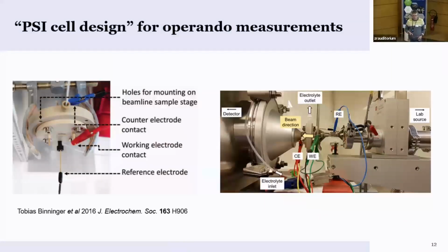Of course, important in this is to have electrochemical cells that allow these measurements. And basically, we use two different configurations of cells. One, which I just call the PSI design, was introduced at the PSI, where you come with a beam. Here you have the electrochemical cell, and the beam comes from here and crosses, so to say, your catalyst layer, which is here. So the beam comes parallel to the surface normal of your catalyst film,